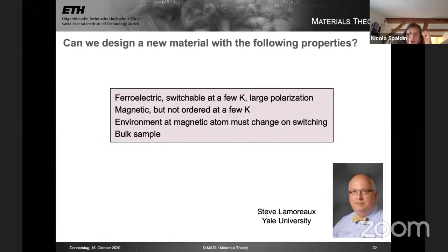So he wanted magnetic moments in there, but no magnetic ordering, even at low temperature. And so here, of course, as we discussed earlier, the rare earths are very good because they're really localized. They don't bond much with the oxygen, so they don't have high ordering temperatures. The environment at the magnetic atom had to change on switching, and he needed a lot of material. So a thin film was not going to be good enough. He wanted a bulk sample.